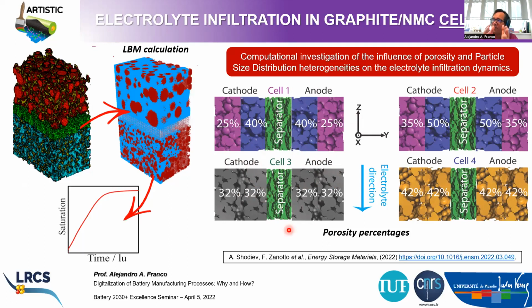Using tomography images as microstructures for these simulations. What we can do here is explore how fast this electrolyte infiltration will go through these different configurations. Here you have electrodes with homogeneous porosity, and here you have electrodes with a gradient of porosity along their thickness.